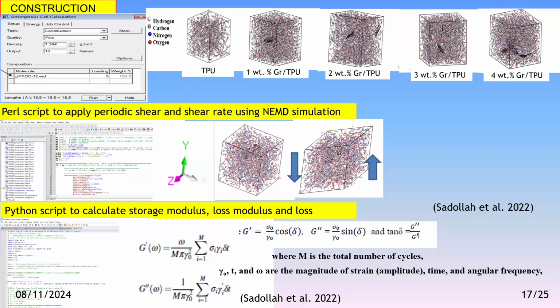But if you go to the simulation, you get an idea which sample is better for viscoelastic property. In our study, you can see that 3 weight percent gives the better viscoelastic property. So if you initially get the idea that 3 weight percent is best, then easily you can develop the 3 weight percent sample for DMA testing, and it is not required to prepare other samples. So it takes less time for sample preparation. From the molecular simulation, you get an idea which weight percentage is preferable. Then you move to prepare and test the 3 weight percent sample.